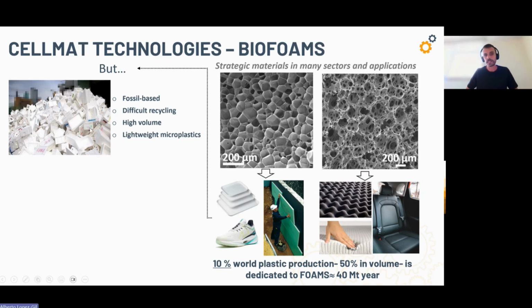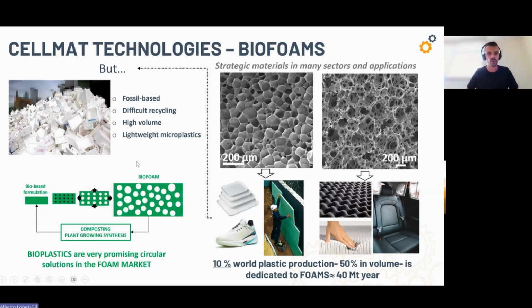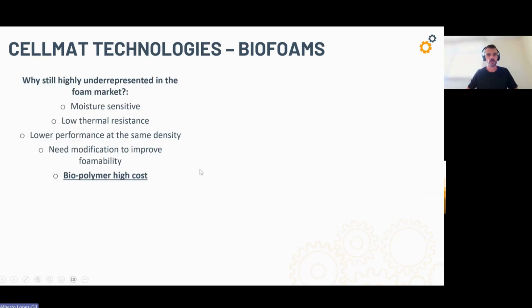And concretely, associated to expanded polystyrene, for instance, they release lightweight microplastics that can be accidentally dispersed in the environment. And this is also a huge concern, specifically linked to foams. This is why we believe in CELLMAT and in general terms that bioplastics are very promising circular solutions in the foam market.